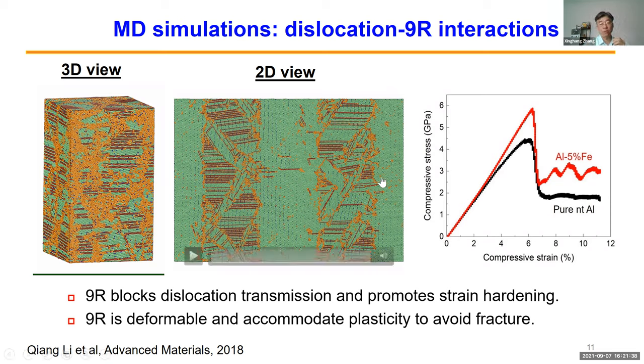What we saw was that this 9R phase evolved. The 9R phase can be partially dismantled, but not completely. So they accommodate plasticity during high-stress deformation. This shows the 9R phase is probably playing two roles. They block dislocation transmission, but they also accommodate plasticity to some extent. So we don't have to worry about fracture.